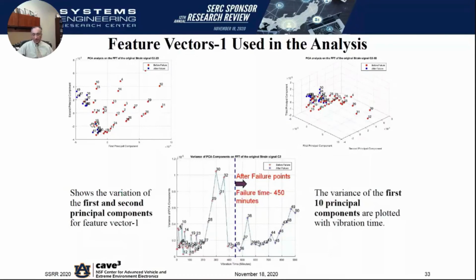So now if I plot the feature vector in the feature space, so that's my principal component space. Ideally, I want assemblies with different amount of accrued damage in different parts of the feature space. So the reds are in different locations than blues. Reds are before failure, blues are after failure. So you can pretty clearly see that one can put the parts with different amount of accrued damage in different parts of the feature space.